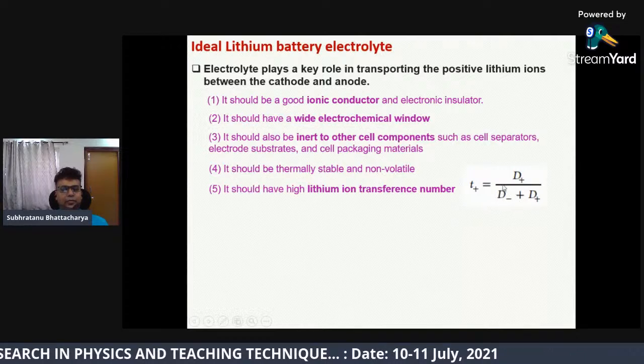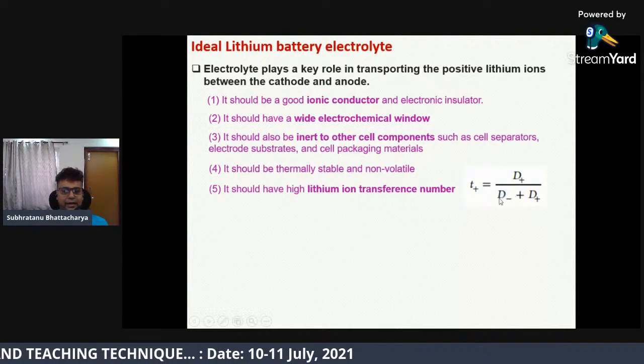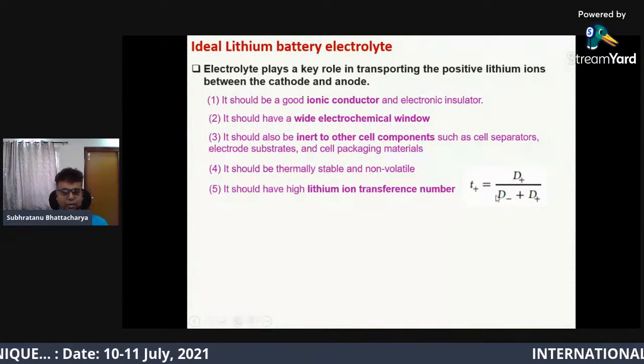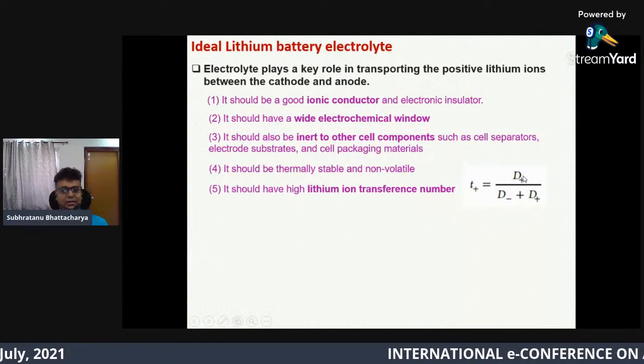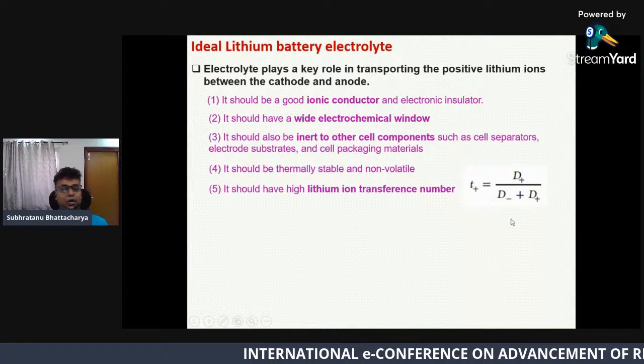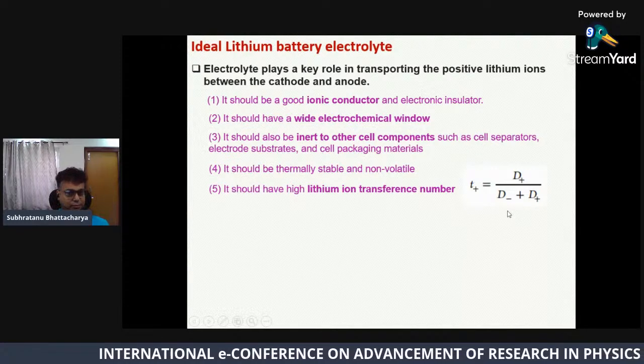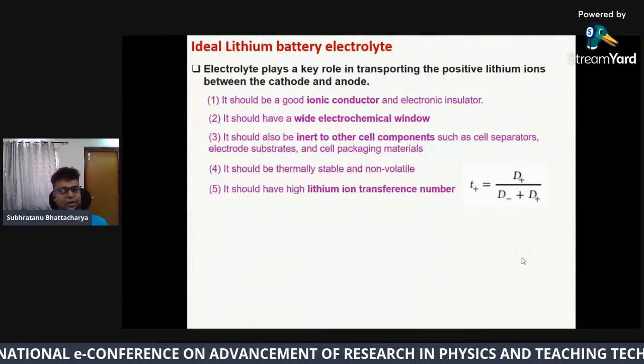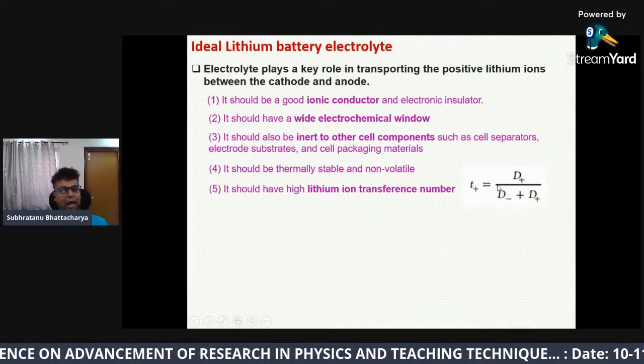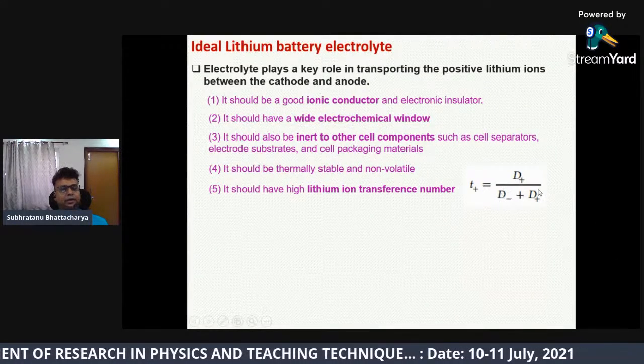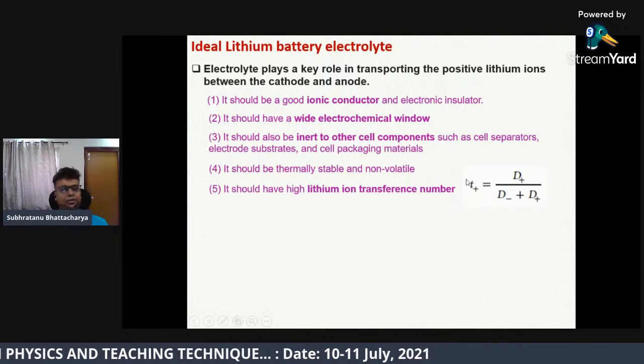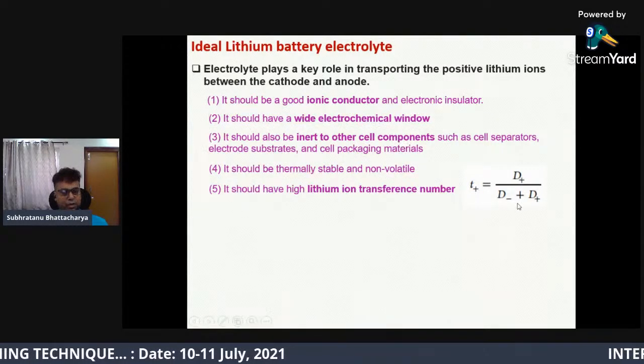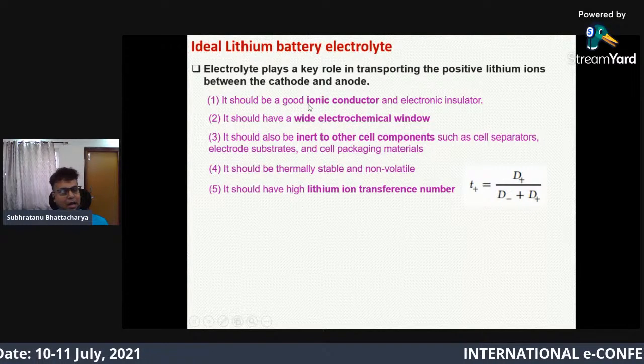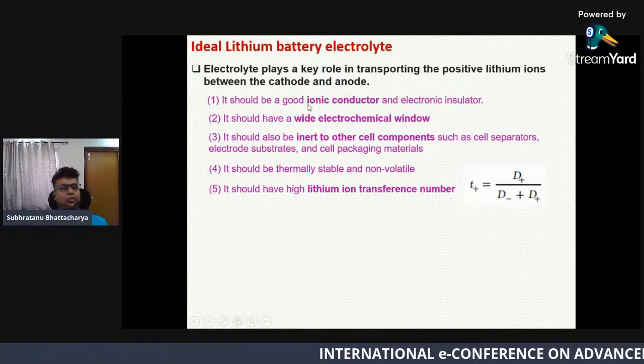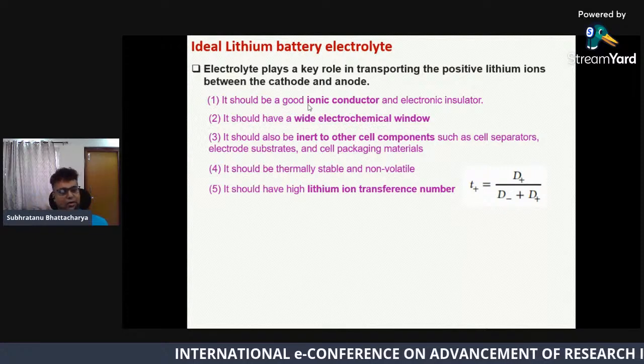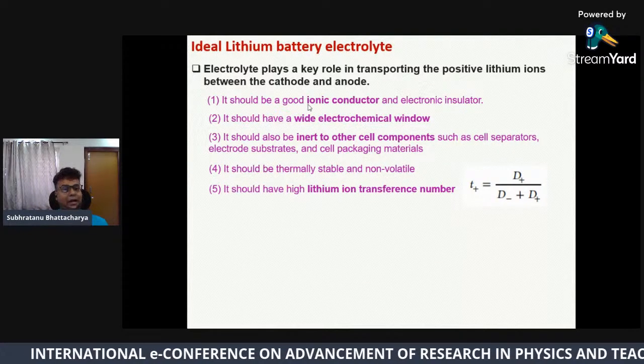If you can neglect the diffusivity of the anion, then your transference number is 1, which means you get ionic conductivity only because of the cation. You can understand this. But if somehow your anionic conductivity becomes higher than the cationic conductivity, then your transference number will be very low. Maybe it is highly conductive, but who is actually contributing this ion conduction? The anion instead of the cation.